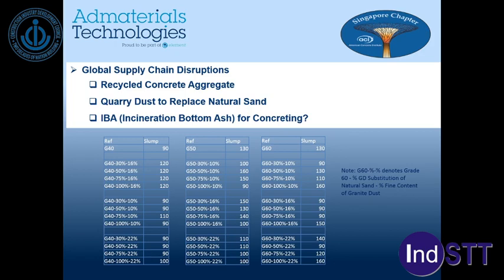So we have to think of other, locally available materials. For example, recycled concrete aggregate and quarry dust to replace natural sand. So IBA, incineration bottom ash, for concreting. Below is a research project we are currently undertaking to study how to use quarry dust to replace natural sand. You can see different fines content and different replacement levels. We can see that workability, meaning slump, is not much affected even if we use 100% and the fines content as high as 22%. The workability is still comparable to natural sand.